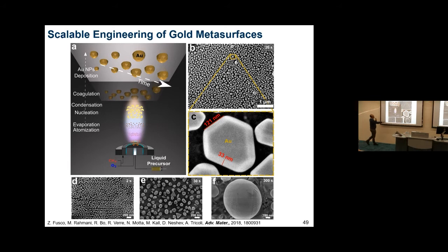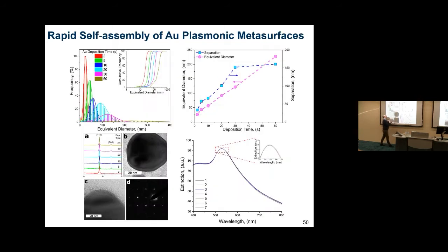We can do this in 2 seconds. We have highly uniform islands distributed over the surface, and we can grow them into bigger and bigger crystals. If you look at the deposition time, from 2 seconds to 60 seconds, we can measure the diameter. There is a distribution, and we also have control over the equivalent diameter and the spacing between these structures.